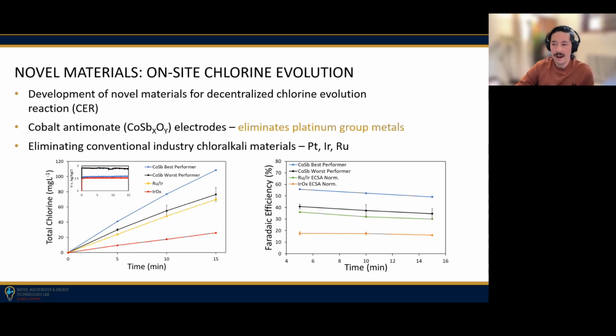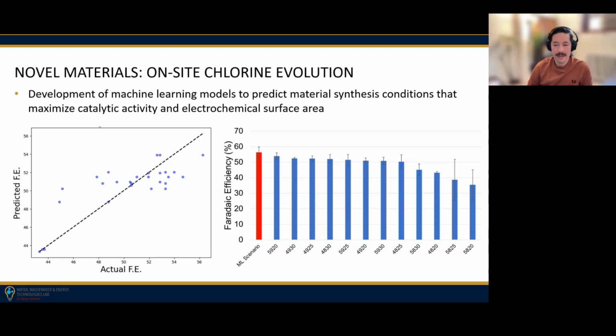So obviously we'd like it to be at 100%, and we've been working and still continue to work on improving that. And some of the techniques that we're using to do that is using machine learning. So developing machine learning models to predict how we can go back into the lab and change our conditions to maximize catalytic activity and electrochemical surface area for better chlorine production. And this is just an example of a Gaussian process regression model that we used. And we basically, all this data in blue, we used to make our machine learning model that then informed us on specific generation conditions. And then we made that electrode that our model said would be good. And we tested it. We can see that, yes, the current efficiency increased a little bit.